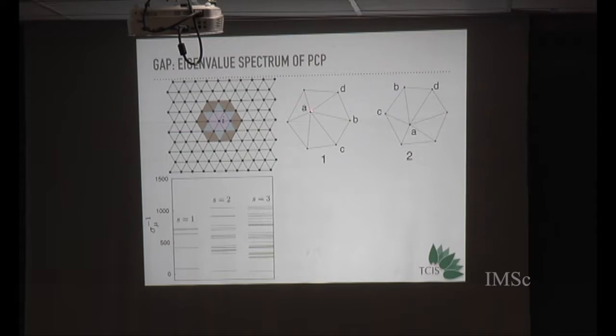And you can see that in the triangular lattice, what happens is that basically it stretches nearest neighbor bonds, and it tries to bring 2 next nearest neighbor particles together. So if I were to continue this, so that AB becomes much larger than CD, and then I cut this bond and I form a bond between C and D, this is exactly a dislocation dipole. Okay. So dislocation theory comes out as a lowest eigenvalue approximation from this entire thing.